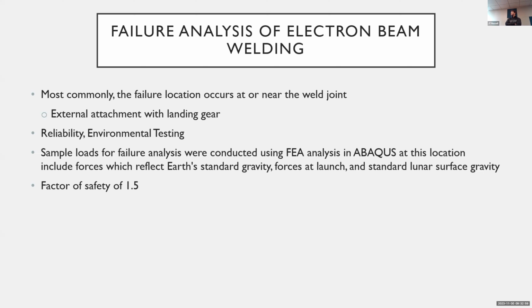But for now, we calculated the sample loads for the failure analysis regarding finite element analysis and Abaqus at the location of the weld to represent forces which would reflect Earth's standard gravity, the forces at launch, and the standard lunar surface gravity with a factor of safety of 1.5. And following this Abaqus experiment, we found that we would have end-to-end mission safety. We found that we would be able to comply with the initial set of requirements we drafted.